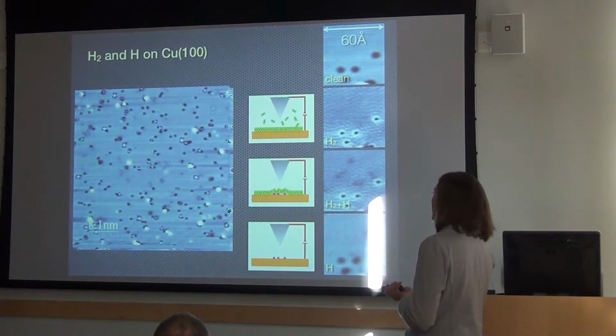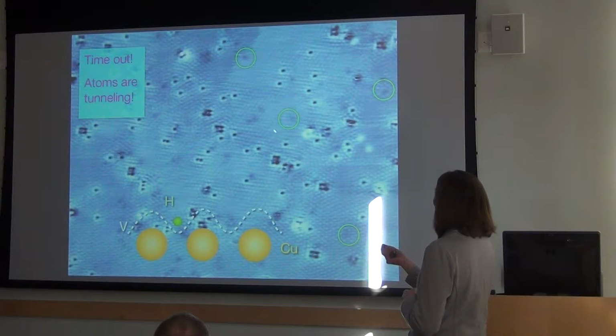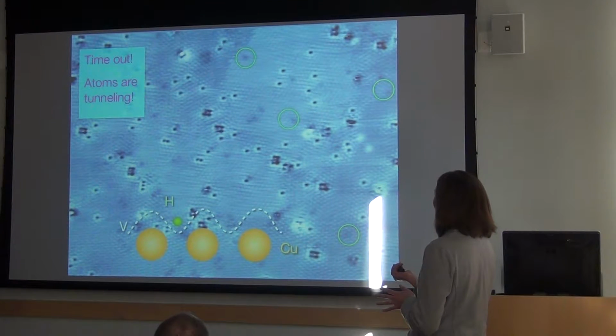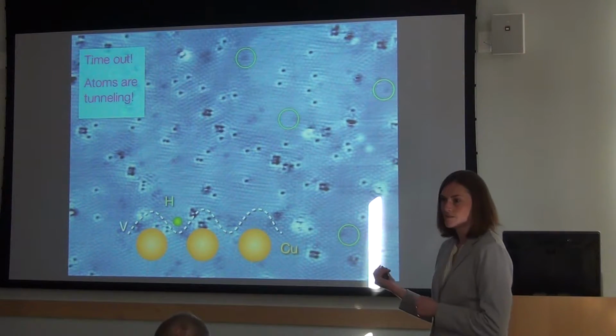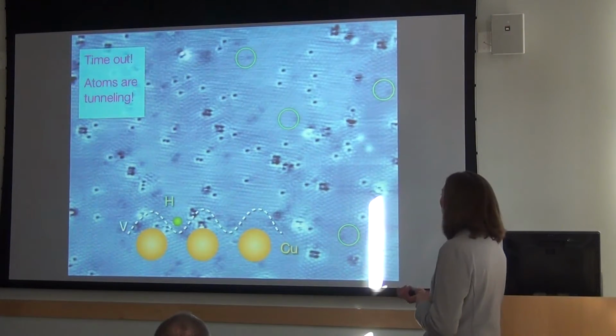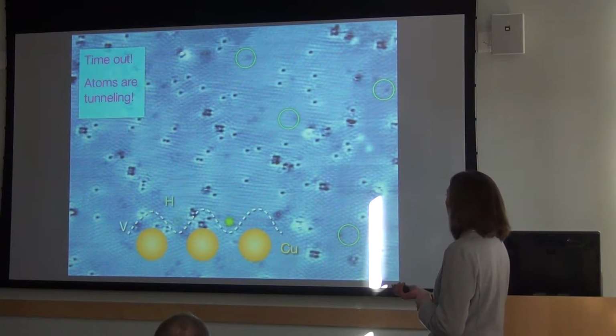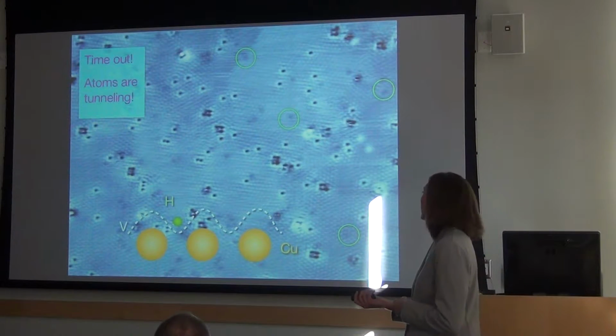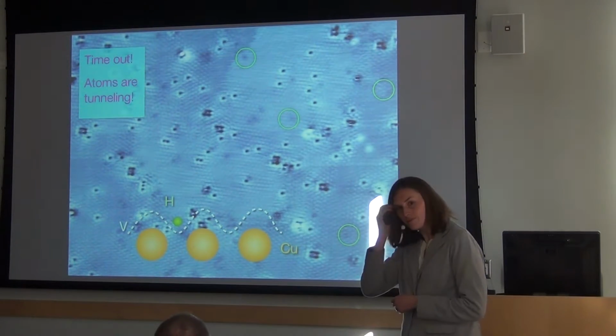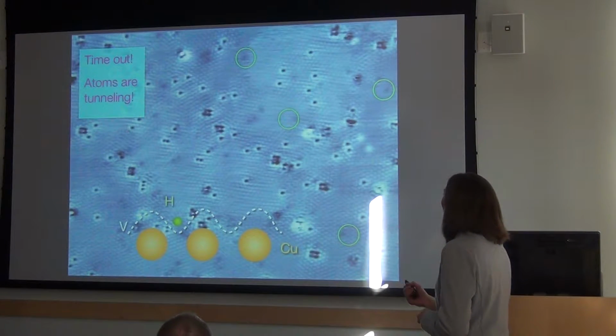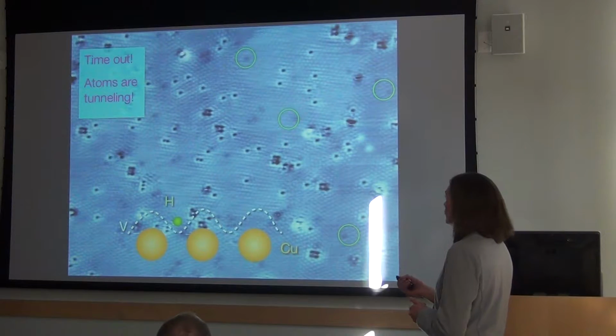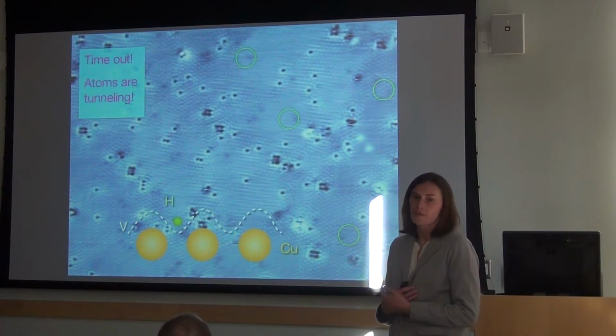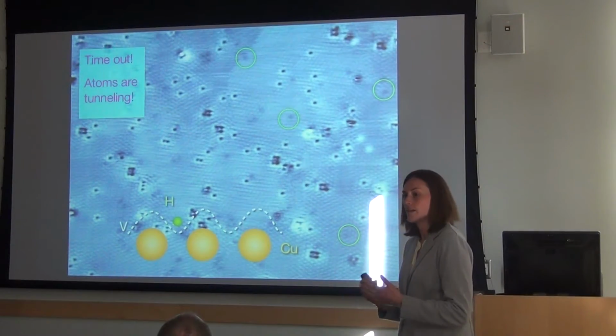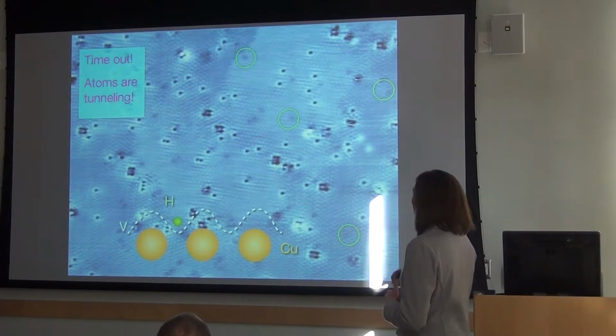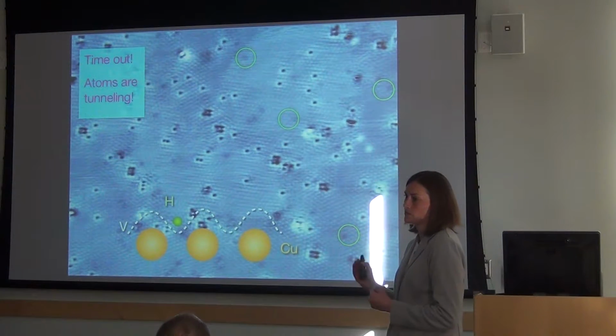And we are convinced this is atomic hydrogen because of a very cool experiment that we were copying. If you look closely in one of these green circles, this is at 5 Kelvin. You can see these little dark spots jumping around, right? What this is actually is atomic tunneling between different sites of the copper lattice. This follows some work that showed this is quantum mechanical tunneling and not thermally activated popping of atoms, on the same system, this copper 100 system, where they dosed atomic hydrogen.